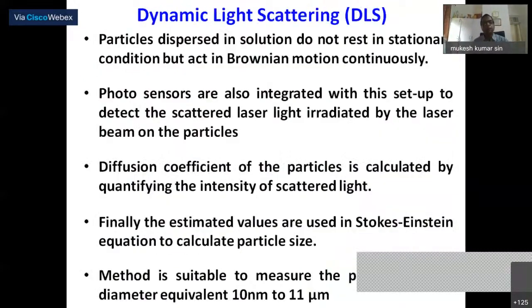As I have already mentioned, there is the dynamic light scattering technique, DLS. This is the most popular technique nowadays. Particles dispersed in solution don't rest in a stationary condition, but act in Brownian motion continuously. This is the base to understand dynamic light scattering. Photosensors are also integrated with this setup to detect the scattered light. The diffusion coefficient is calculated from the fluctuation of the intensity of scattered light. Finally, the estimated values are used in the Stokes-Einstein equation to calculate the particle size.